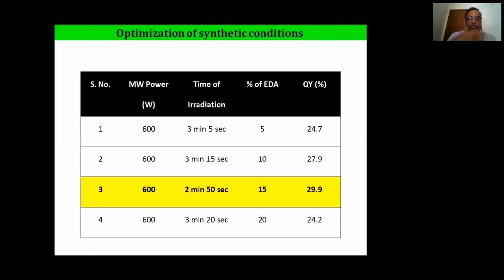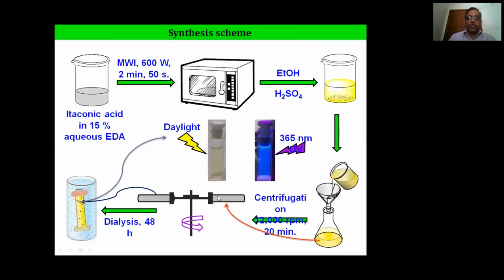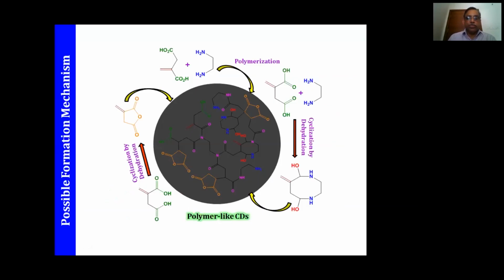As usual, we standardized and optimized the synthetic parameters - the wattage of the microwave and the time duration. We found that a microwave power of around 600 and 2 to 3 minutes is ideal to synthesize this material. Same methodology: itaconic acid, microwave, get the product, centrifuge, dialysis, then use it for characterization and application studies.